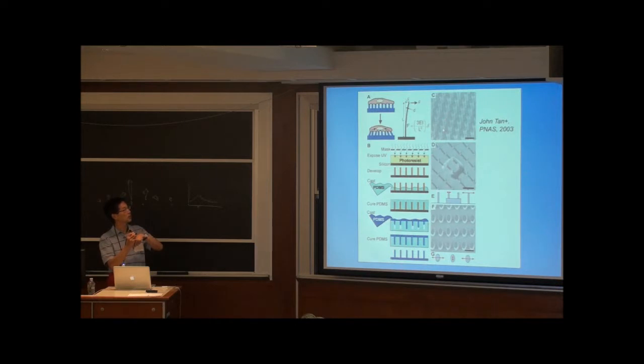And you can see these pillars, turns out, are not perfectly vertical. You notice that they're a little bit conical. And they're conical because the light that was coming in through those pinholes was not perfectly vertical, okay?